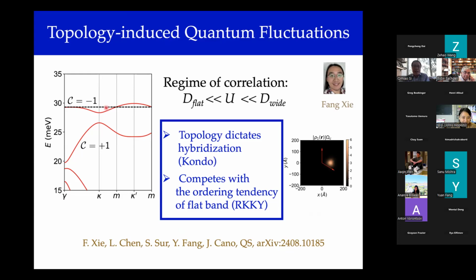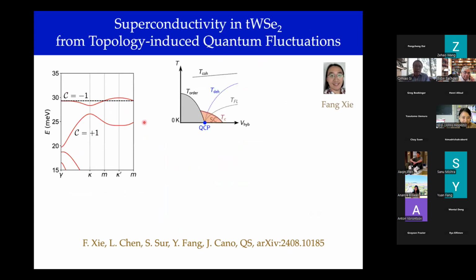And so here, it's a topology that dictates that real space orbitals must be hybridized in the right regime of correlations and in the natural regime of correlations. And this hybridization represents quantum fluctuations that's dictated by band topology. And that leads to a competition with the RKKY. So we adopted this scheme to show that in a model that is introduced to describe this setting, we can realize electronic order associated with a flat band and tune the hybridization to increase the hybridization to enhance quantum fluctuations to get a system out of electronic order.